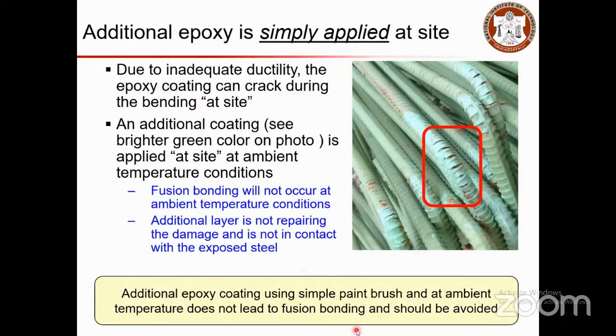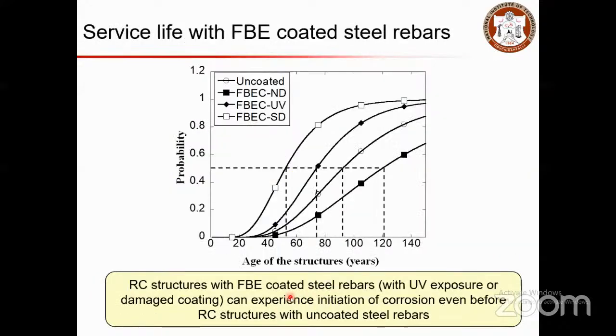So additional epoxy coating using a simple paintbrush at ambient temperature does not lead to fusion bonding, and it should be avoided. There is a study on the service life of this fusion bonded epoxy coated steel rebar. You can see this is the uncoated rebar, and this is the coated rebar without damage. And when you have these coated rebars exposed to atmospheric conditions, lying at the site for a long duration, there will be degradation due to ultraviolet rays and direct sun exposure as well. So this indicates no damage, this indicates ultraviolet damage, and this SD condition indicates the surface damage of your rebars.